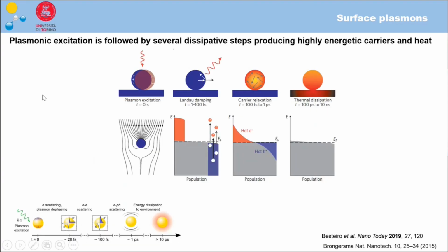And to go more into the fundamentals of plasmonic materials, the fundamental property of a plasmonic material when it starts to absorb light is that it is able to concentrate light from the far field to the near field, and the optical cross-section is much higher than the geometric cross-section. And this happens only when we have nanoparticles with deeply subwavelength size. This excites the conducting electrons on the surface of the material and creates very highly intense electromagnetic fields, the hotspots, which can be used for many things.